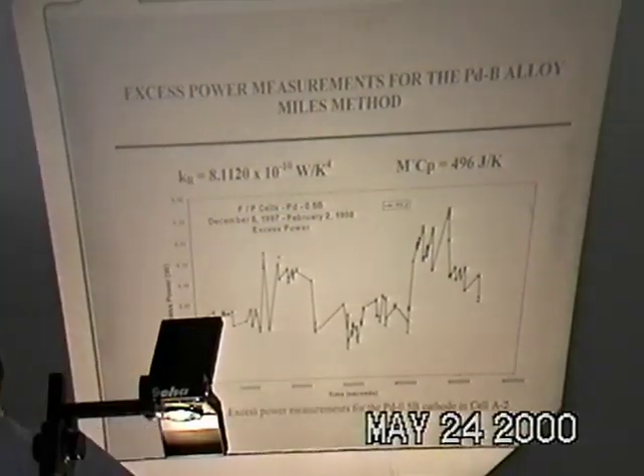Now, when I applied the same method to the palladium boron, I got a different result. There was excess power. There's even a small excess power starting early in the experiment, but there were two large bands of excess power. A large band through this region, then less excess power through a large time period, and then another band of excess power later in the experiment. And using this value. Now, as Martin Fleischmann will mention tomorrow, perhaps this constant is too small. It should be around 8.5 instead of 8.1. And this value should be around 450. But I do have the data